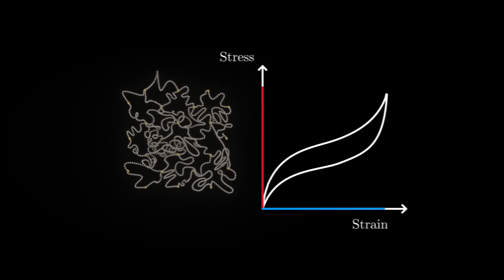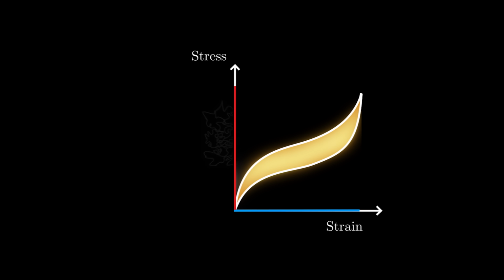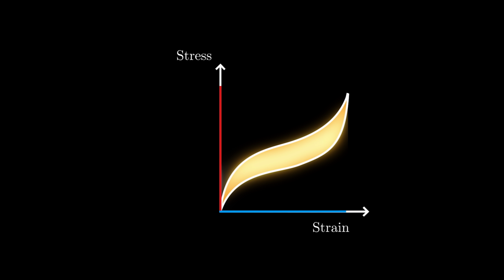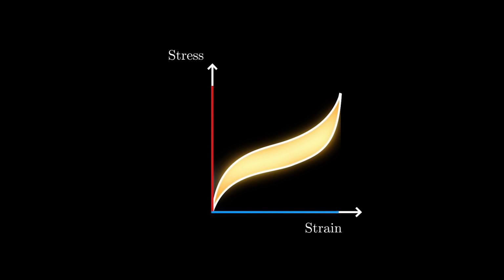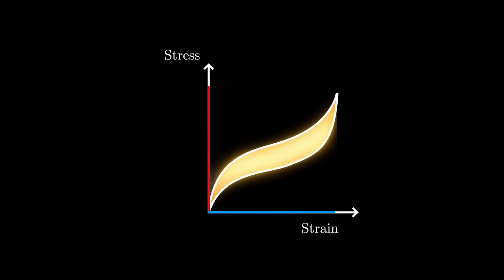How do you dissolve the crystals? You've got to take energy from somewhere to dissolve crystals. You cool the rubber band down. The reason the two curves are different is because it takes more energy to align the polymers than it does for the polymers to curl back up. And this energy difference is exactly the heat that's released over a full cycle.